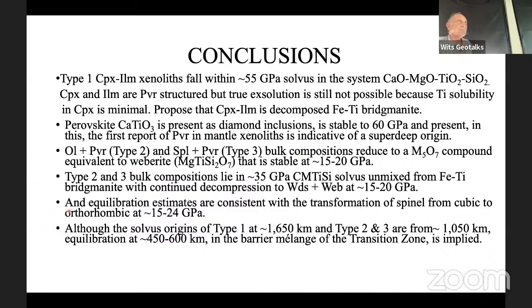The type 2 and 3 bulk compositions more realistically lie, in my view, at 35 GPa. But with continued decompression, they will fall into the 15 to 20. So in other words, they're in the transitions. And equilibrium estimates are consistent with the transformation of spinel from cubic to orthorhombic. That looks good. And although the solvus origins of type 1 and type 2 and 3 are from over 1,000